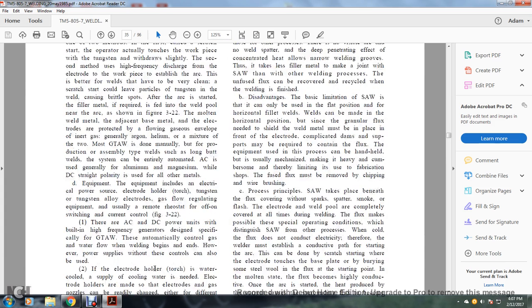Most gas tungsten arc welding is done manually, but for production of assembly-type welds, such as long butt welds, the system can be entirely automated. AC is used generally for aluminum and magnesium, while DC straight polarity is used for all other metals. The equipment includes the electrical power source, electrode holder or torch, tungsten and tungsten alloy electrodes, gas flow regulating equipment, and usually a remote rheostat or on-off switch for current control.